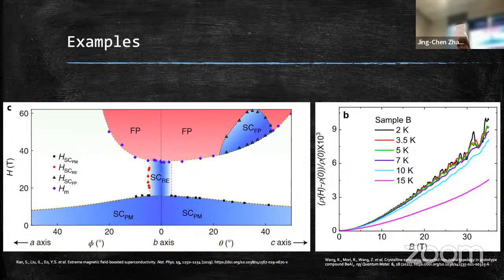And by same unit cell, I mean there's less than a 0.5% difference between lattice parameters. It's basically the same thing. Yes, europium has magnetism, but the strontium case does not have magnetism, and it's still true. You still get charge density waves, and you still get oscillations that die off at super high temperatures. Why? There's no commonly agreed theories on that.